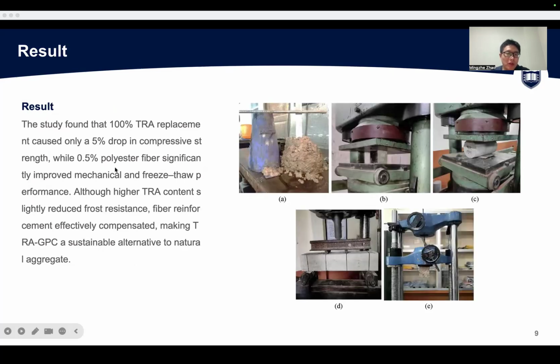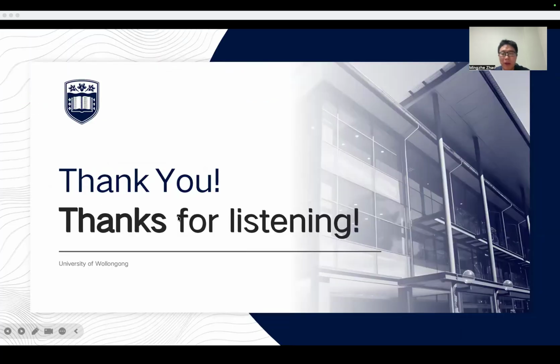So the results found that 100% TRA replacement caused only a 5% drop in compressive strength, while 0.5% polyester fiber significantly improved the mechanical and freeze and thaw performance. Although higher TRA content significantly reduced the frost resistance, fiber reinforcement effectively compensated, making TRA GPC a sustainable alternative to natural aggregate. So that's all for my report. Thank you. Thanks for listening.